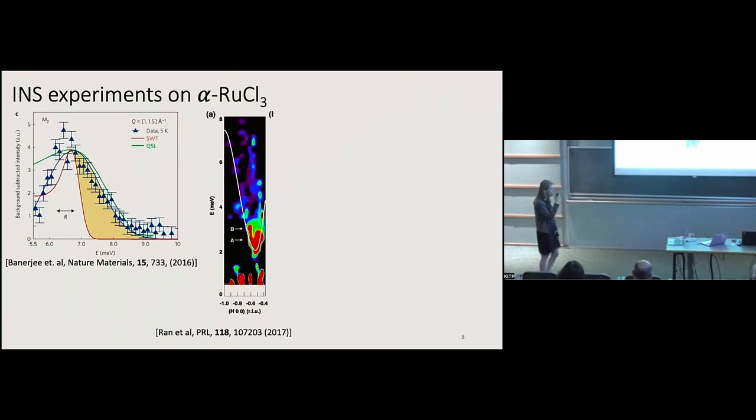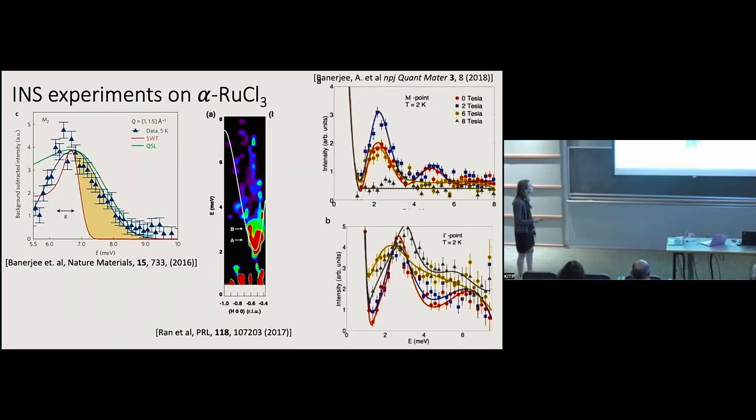This paper's story was, I can fit the spin wave spectra and I see that there's a large Kitaev term, so maybe it's close to the Kitaev phase. And then, ruthenium trichloride does order at low temperatures, but if I put on an in-plane field, I can destroy the order. So once I've destroyed this order at 8 Tesla, you still have this broad feature at the gamma point.